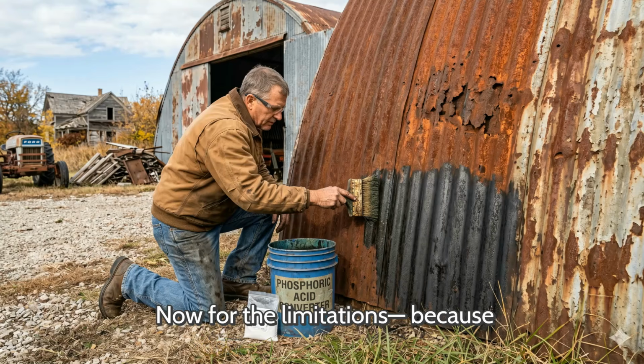Now for the limitations, because anyone who tells you this works on everything forever without any caveats is lying to you, and you deserve better than that. This method does not repair structural damage. If your steel panels have rusted completely through, actual holes, visible perforations, sections where you can poke a finger through, chemistry cannot fix that. Conversion stabilizes surface rust and moderately deep pitting. It cannot fill voids. Panels with through rust need to be replaced or patched before conversion treatment.